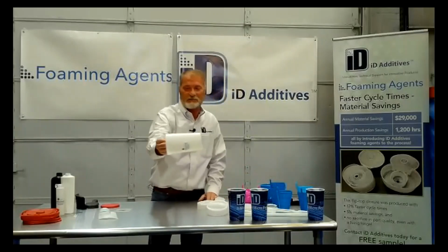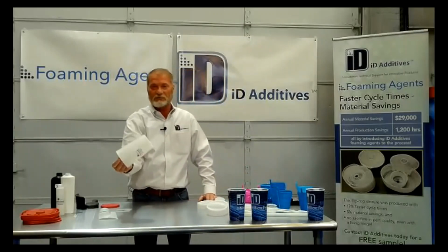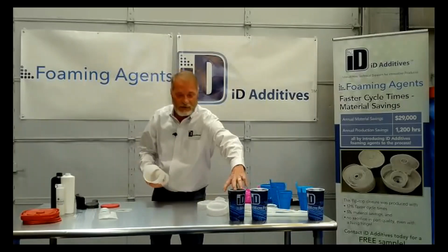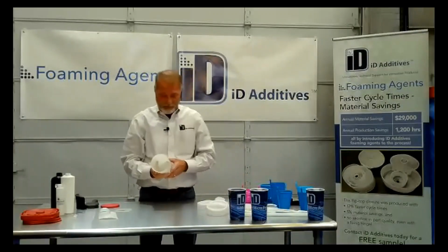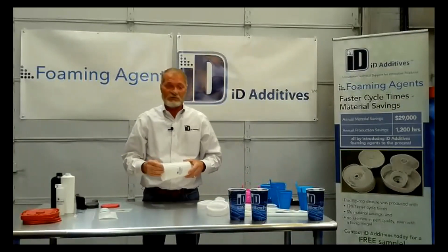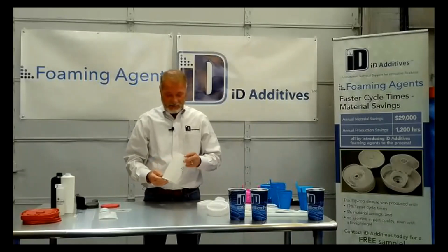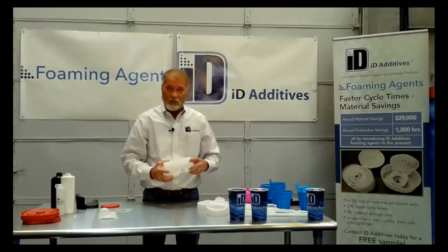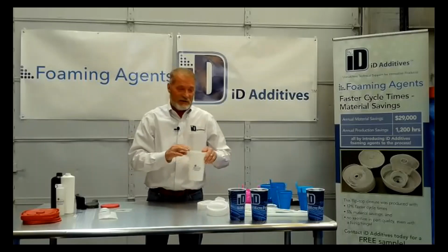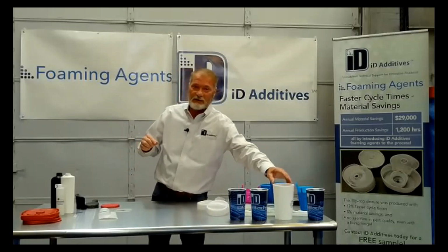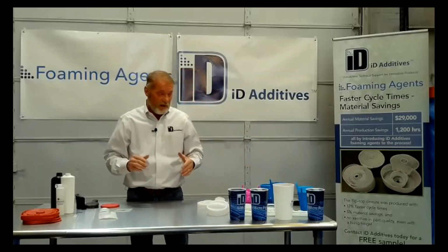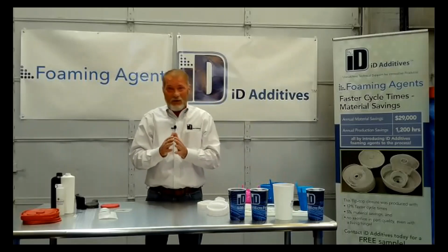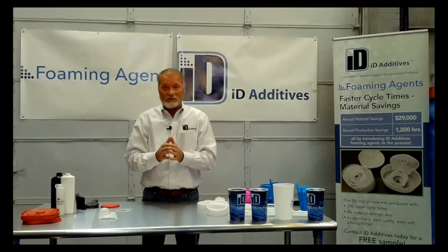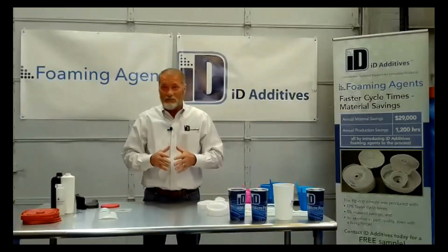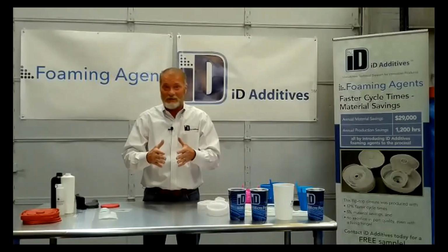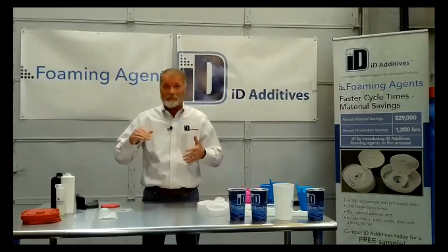This doesn't have a splay one, but it's loaded with bubbles. And of course they do this kind of molding, but I just wanted to show you what it looked like without that. And it is loaded with bubbles all the way up to the top. But again, you're only putting bubbles in the middle of a wall, so that middle is only going to hold so many bubbles. And if you start adding more bubbles, they're going to make it to the surface and they're going to splay.